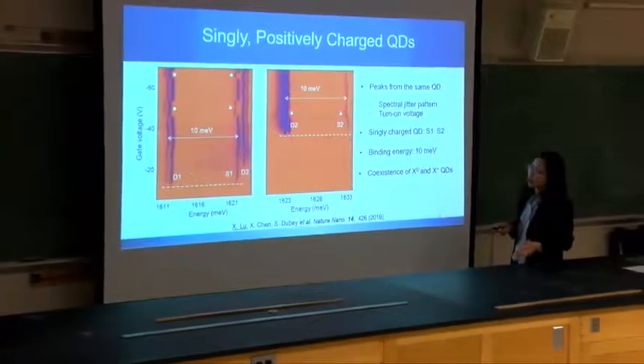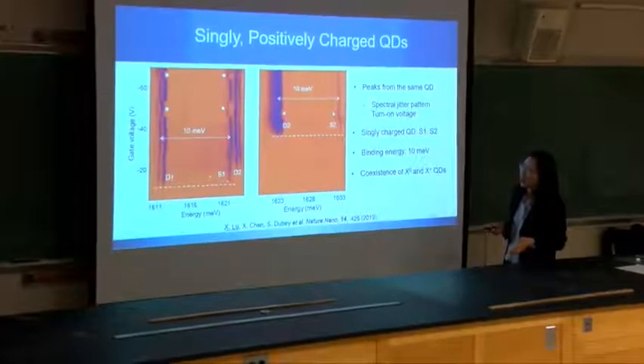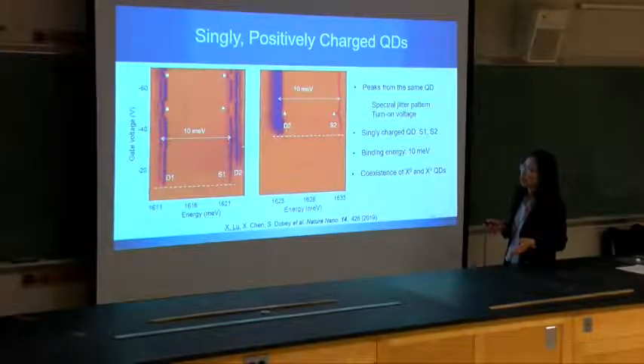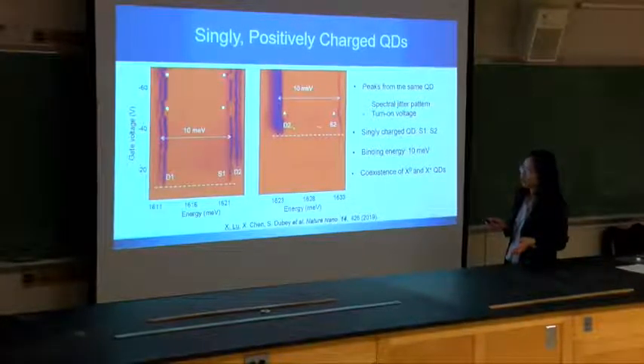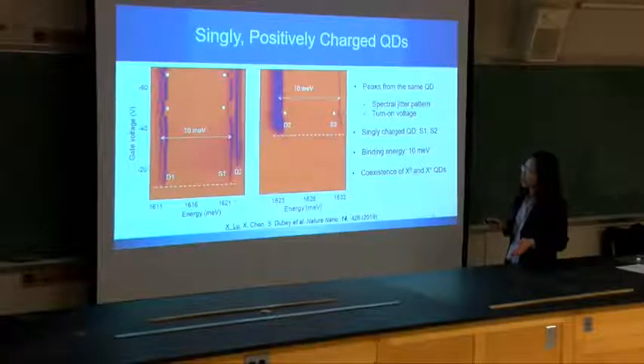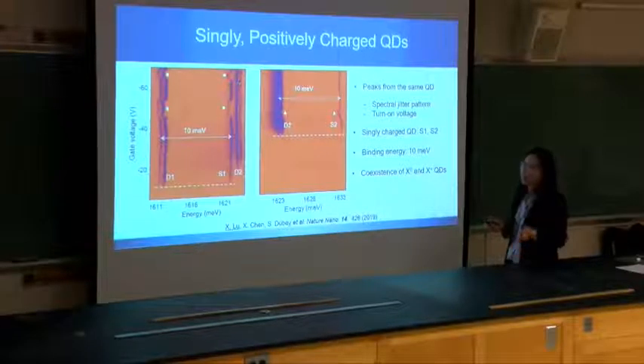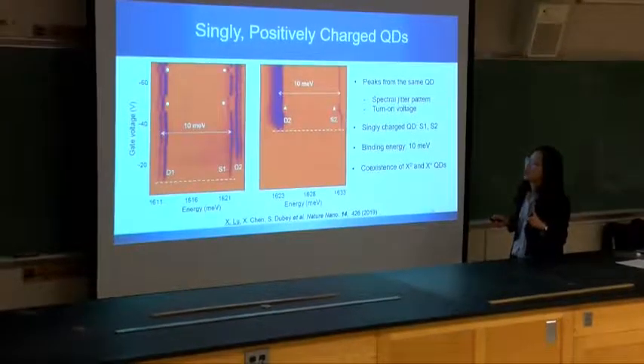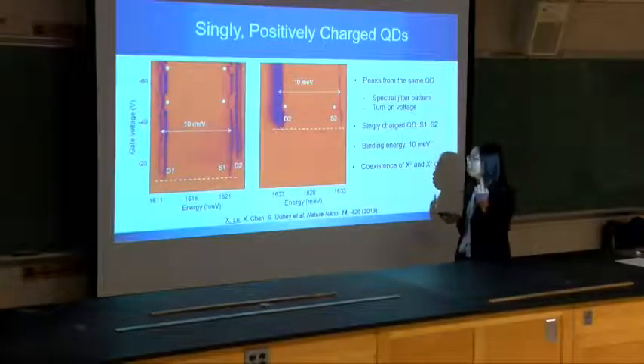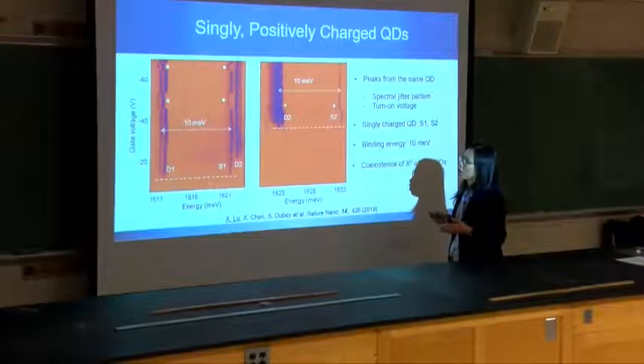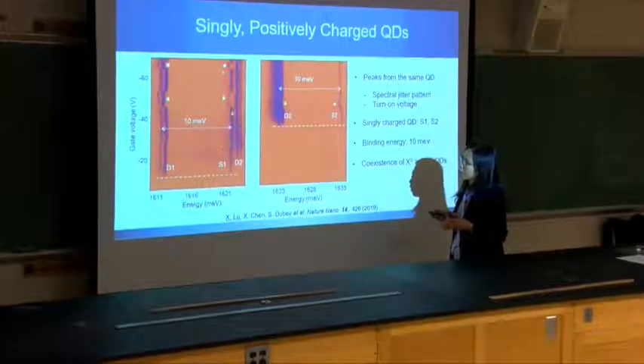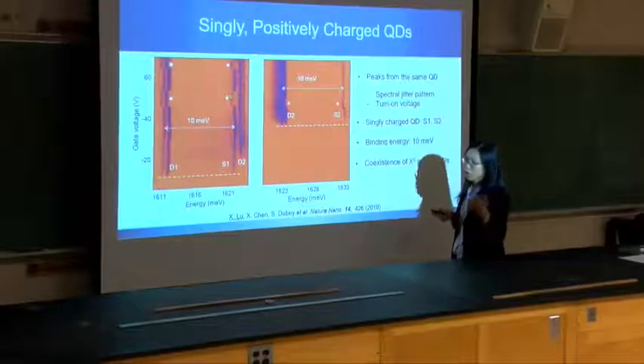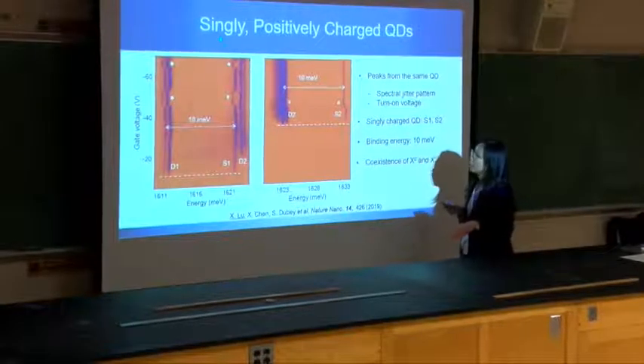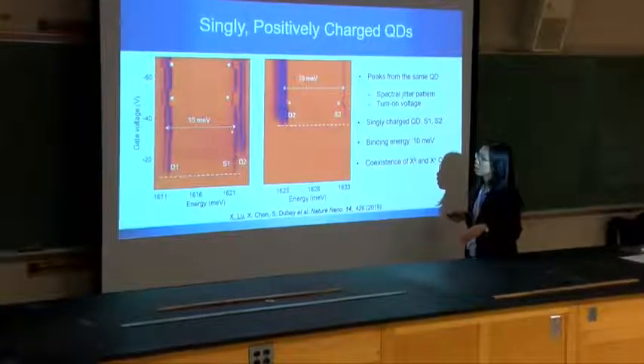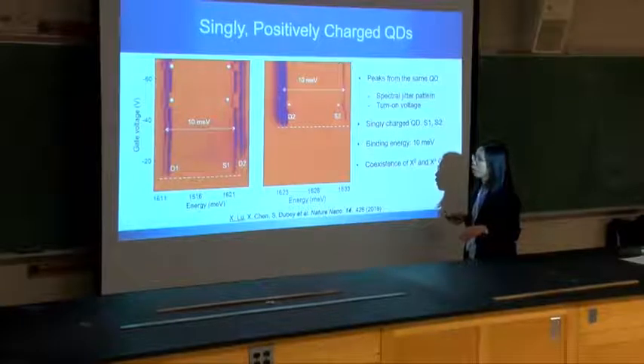In the meantime, we see that about 10 milli electron volts above D1 and D2, there's a single peak, which wanders in the same pattern. It has just one peak. So the indication to us is that it could be a positively charged single photon emitter, as there's no exchange and there's no splitting. So that's what we assigned it to be, the singly positively charged quantum dot.